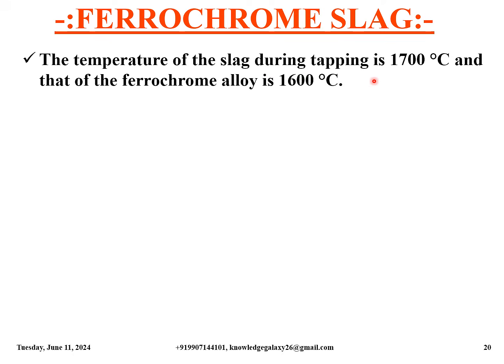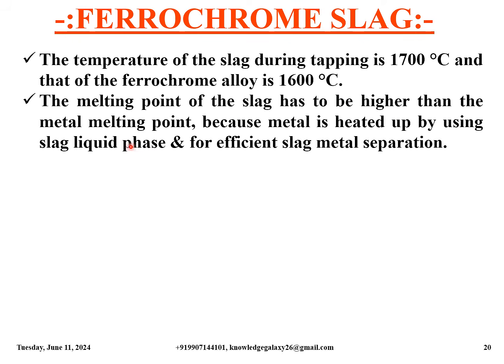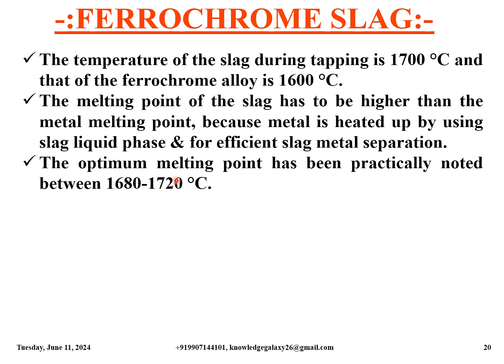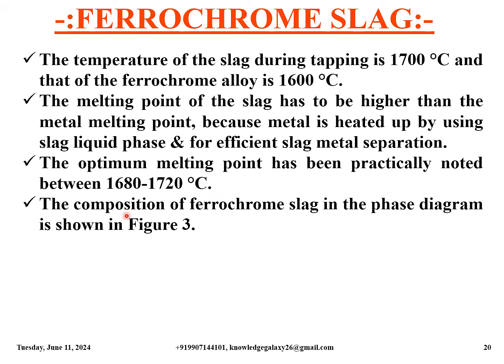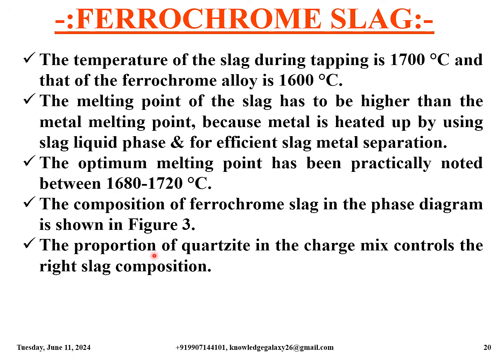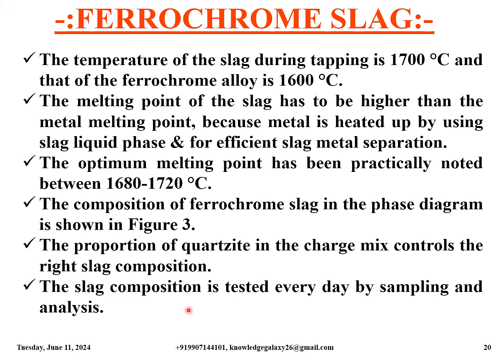The temperature of the slag during tapping is 1700 degrees Celsius, and that of the ferrochrome alloy is 1600 degrees Celsius. The melting point of the slag has to be higher than the metal melting point because the metal is heated up by the slag liquid phase, and for efficient slag-metal separation. The optimum melting point has been practically noted between 1680 and 1720 degrees Celsius. The composition of ferrochrome slag in the phase diagram is shown in figure 3 in the coming slides. The proportion of quartzite in the charge mix controls the right slag composition. The slag composition is tested every day by sampling and analysis.